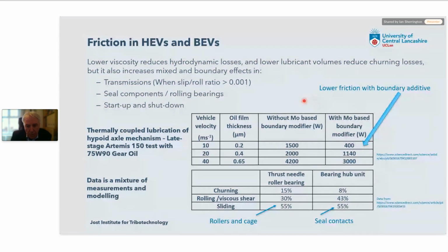So without the boundary modifier, the power losses are given in this column here, but with the boundary additive reducing the friction, you can see the friction comes down enormously. So obviously it's speed dependent. At faster speeds, the difference is less when we get a more complete fluid film. But at lower speeds, we get quite considerable changes when we introduce this boundary additive. That means that boundary friction is present, and that incorporating the additive brings this significant gain in reduction of friction.